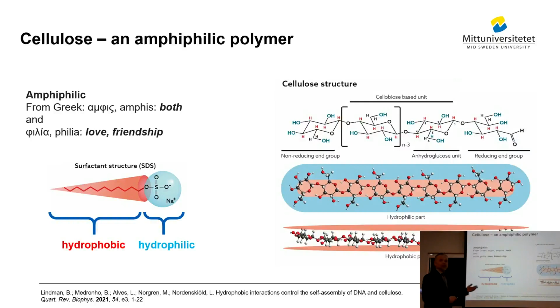But in cellulose, you don't see such outspoken structures. If you look at the cellulose polymer from different angles, you can see that you have an overrepresentation of the CH bonds in one plane, and an overrepresentation of OH groups in another plane, which means that it has somewhat different properties depending on which plane of the molecule you look at. And that will affect how it associates, for instance, or is dissolved.